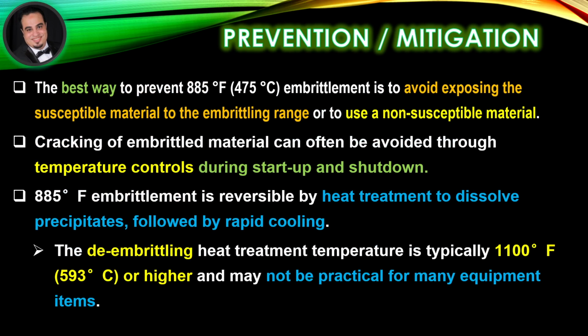Prevention and mitigation. The best way to prevent 885 degrees Fahrenheit embrittlement is to avoid exposing the susceptible material to the embrittling range, or to use a non-susceptible material. Cracking of embrittled material can often be avoided through temperature controls during startup and shutdown. 885 degrees Fahrenheit embrittlement is reversible by heat treatment to dissolve precipitates, followed by rapid cooling. The de-embrittling heat treatment temperature is typically 1100 degrees Fahrenheit or higher, and may not be practical for many equipment items.